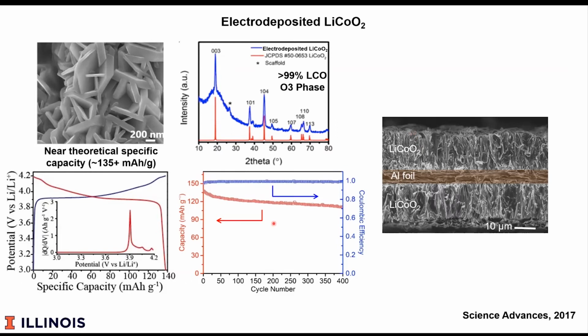Does it work? Well, this is the cycling. So over 400 cycles, it's lost about 10 to 15% of its capacity. So that's very competitive with today's systems. By X-ray diffraction, it's over 99% pure. I'll show more sophisticated material analysis shortly.